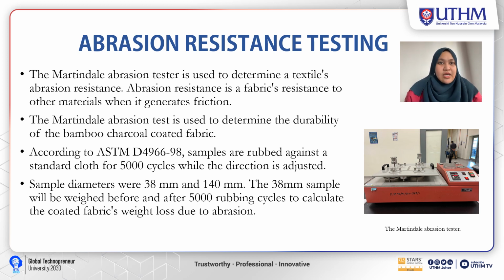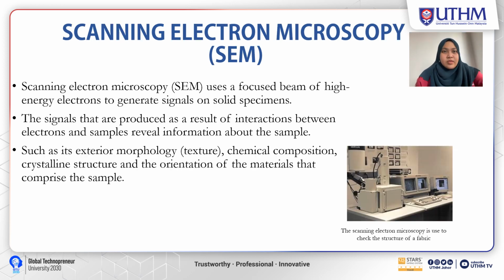According to ASTM D4966-98, samples are rubbed against a standard cloth for 5,000 cycles, with the direction adjusted. Sample diameters were 38 and 140 mm. The 38 mm sample is weighed before and after 5,000 rubbing cycles to calculate the coated fabric's weight loss due to abrasion. The picture shows the Martindale abrasion tester.